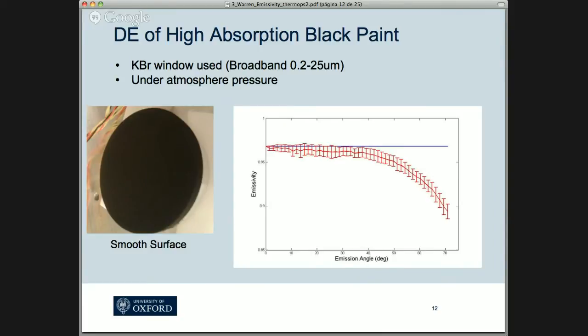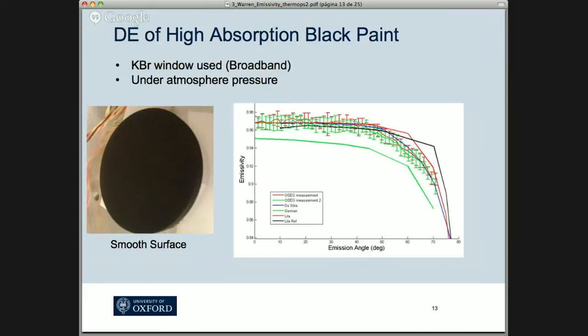So I managed to find similar measurements that have been made before by similar setups. And as you can see, there's actually quite a spread in the measurements. I think that's probably due to the slightly different textures of the paint on all the different surfaces. But it's nice to see that fit quite nicely inside all of this spread. So I tried to model this just using a simple Fresnel model. Blue line is the measurements we made, red line is the Fresnel model. And as you can see, it didn't fit very well.